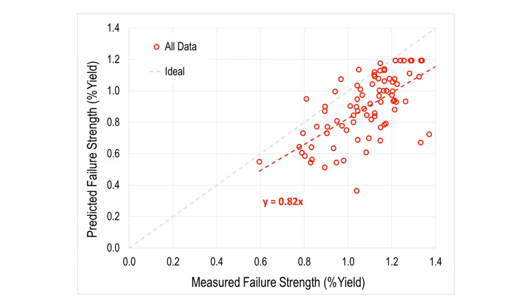So what you'll see there is our data tends to be lower than the unity line, lower than the diagonal line going through the middle of the plot, indicating that on average, modified B31G is, relatively speaking, a conservative model. We do see a few data points that are above that diagonal line, indicating non-conservative and potentially unsafe predictions, but the great majority of them are below the line, and these represent conservative predictions, though some of them are conservative enough that we would perhaps be spending an awful lot of money if we were to dig them all up as pipeline operators.